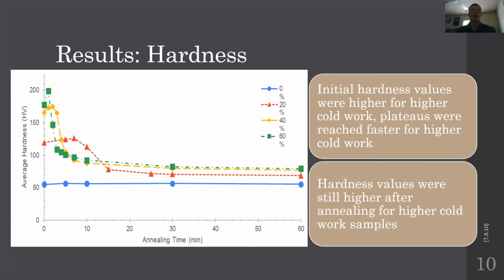And finally, from this data, we can also see that our hardness values after annealing are still higher for all of our cold work samples. They're higher than our uncold worked sample. And this is related to what Christopher talked about on the last slide with the grain size. And it really lends some support to the fact that there is a partial recovery, but not complete, because our properties did not return to their expected value.